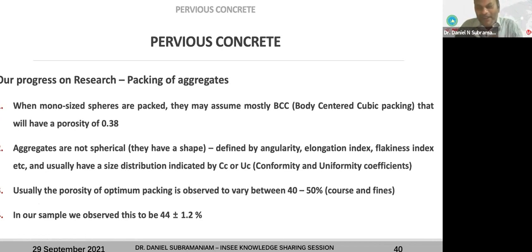Now when it comes to aggregate packing, you will also have a lot of impact. Now we assume all this of BCC, FCC, and all that, considering that it's going to be spherical particles. But in the general sense, it's not. They are not spherical. They are very shapy. So, for example, flaky, elongated, and angular particles. So they are not going to have the same packing as you would expect if you put some marbles into a jar.